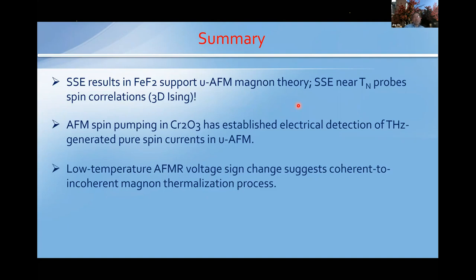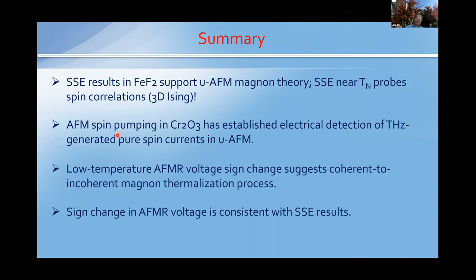Generated the voltage. Okay, so at low temperature antiferromagnetic resonance, there's a sign change that suggests this coherent to incoherent magnon thermalization process, which is important in chromium oxide. And the sign change of the antiferromagnetic resonance voltage can be explained by the spin Seebeck contribution at lower temperature. I should also point out for the spin pumping, in April, I believe, the Central Florida group also reported very nice spin pumping results in manganese difluoride.